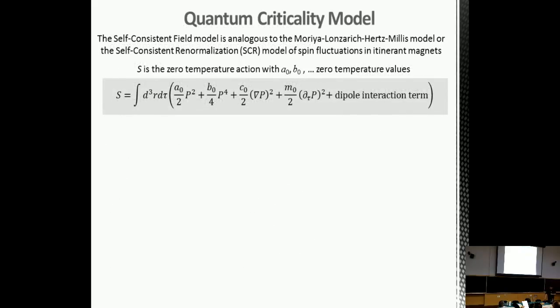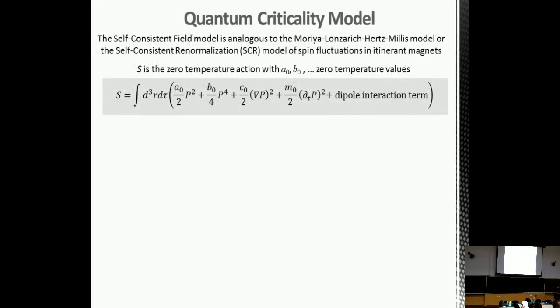So in order to understand the yellow region in ferroelectrics, I'm not going to go into detail of the theory today, but just to outline the kind of models which are used to do this. So here we have a free energy or action expanded in the order parameter, which is the polarization, up to fourth order. We have a time-dependent gradient term and a spatial gradient term here. And we also have, as I mentioned, anisotropic long-range dipole interactions.